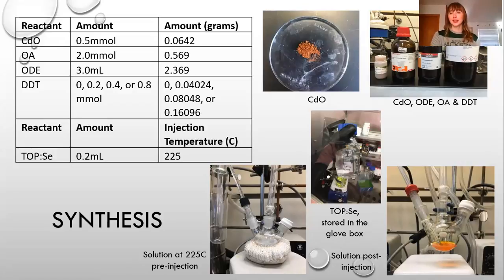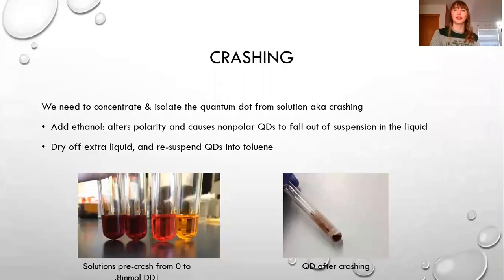So that's the initial synthesis of our quantum dot solutions. I then extract those from the flask. They're cooled down and kept in a vacuum test tube, but then we have to crash it. Crashing it basically means that we're extracting our quantum dots from solution and concentrating them. So we use ethanol to do this.